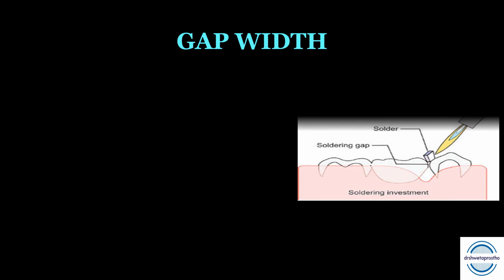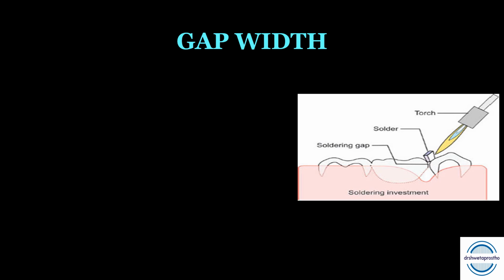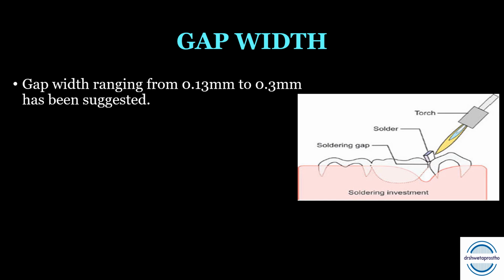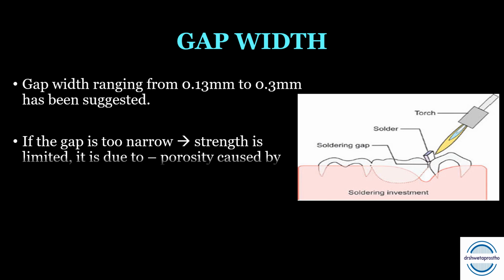Next is the gap width. The gap between the two metal parts is very important. It should be optimum for the proper flow of the solder, giving strength to the joint. A gap width ranging from 0.13 to 0.3 millimeter has been suggested as optimum. If the gap is too narrow, strength is limited because porosity will be there due to incomplete flow of the solder metal and flux inclusion.